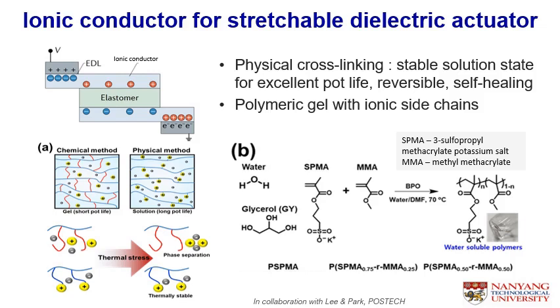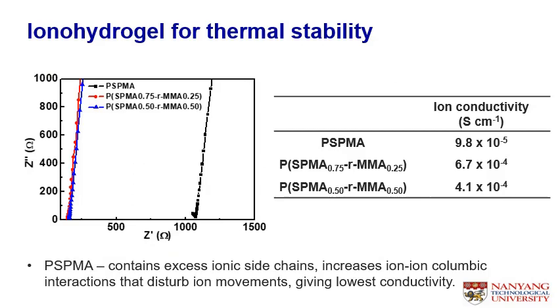The polymeric gel has an ionic component at the side chain. For example, over here with the methyl methacrylate and the sulfopropyl methacrylate potassium salt, we created a water-soluble polymer. Based on different weight% of MMA, we studied the thermal stability of this actuator. As we can see here, the ionic conductivity of the ionohydrogel can be improved with the optimum content of MMA. For the pure PSPMA, it contains excessive ionic side chains that increase the ion-ion Coulombic interaction, and therefore it gives the lowest conductivity.